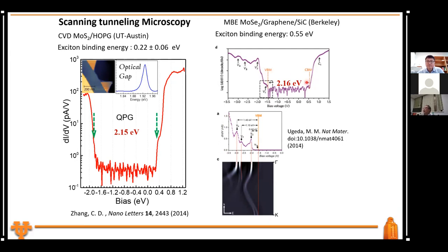And that they can determine the quasi-particle band gap precisely. In that case, for MoSe2, they found the exciton binding energy is about 0.55 eV. So there has been a lot of debate over who is correct. But one can say, well, not every sample can have both ARPES and STM to look at it.